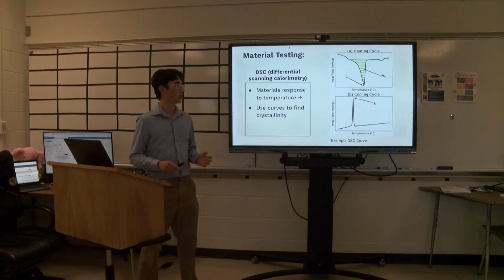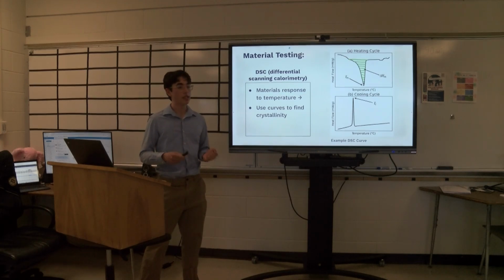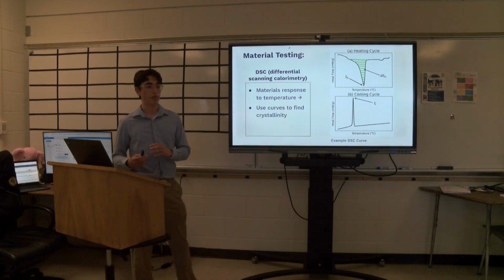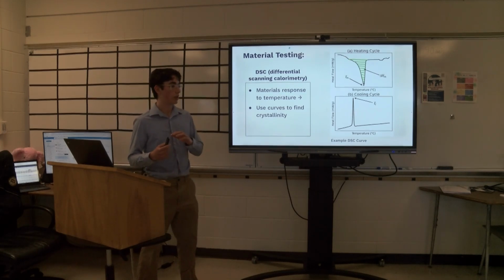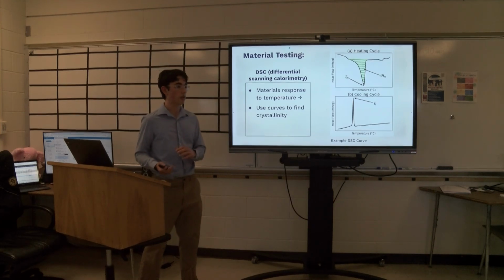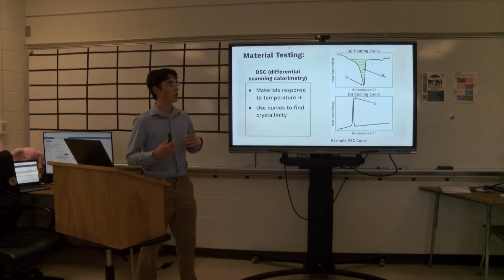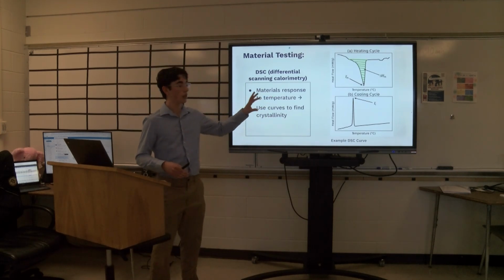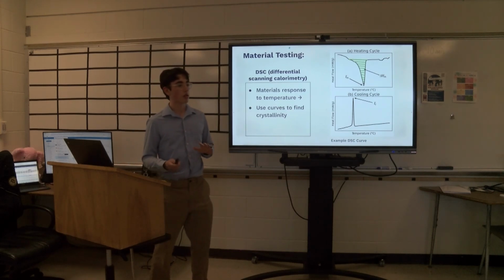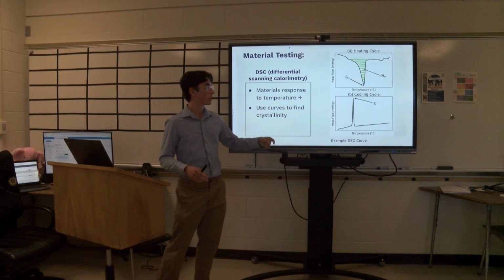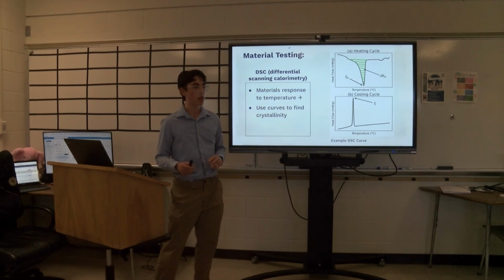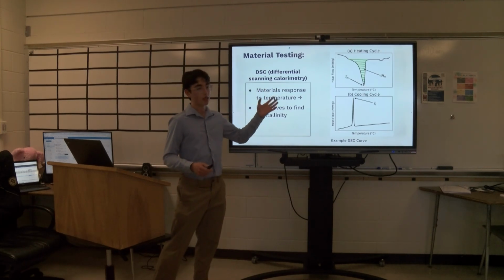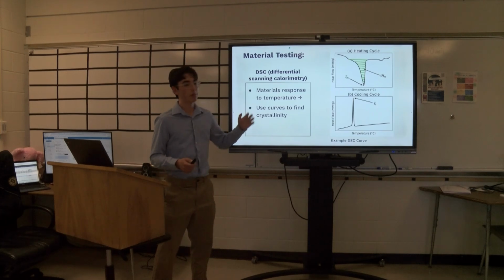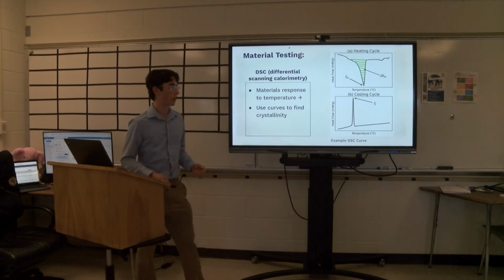Now moving on to material testing, I chose the DSC test to actually determine the percent crystallinity with a numerical value, as the other ones were only indicators. And these generate DSC curves, which you'll see on the left in the example, which are a little daunting to look at at first, but the main things I'm really looking at are the peak crystallization temperature, melting temperature, and the enthalpy of melting, which is essentially the area of the melting peak. And the enthalpy of melting is used to actually calculate the percent crystallinity.